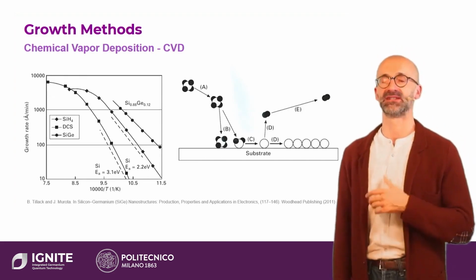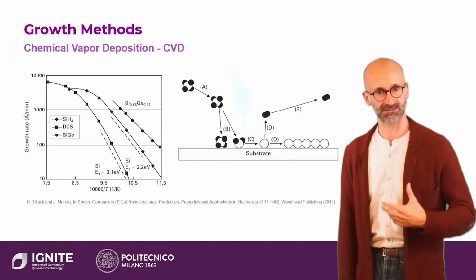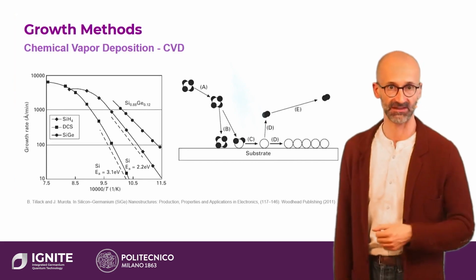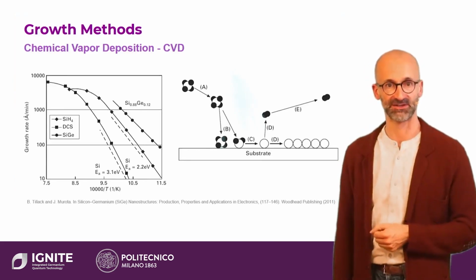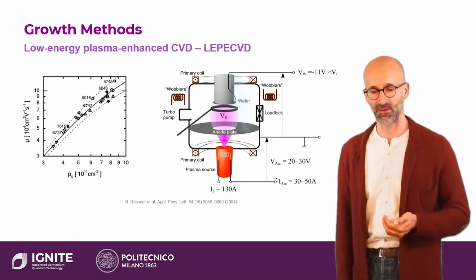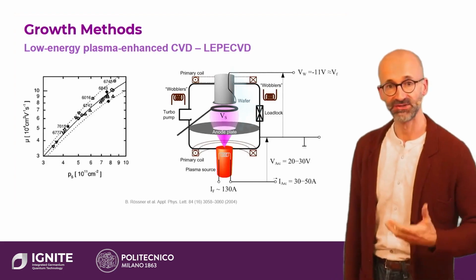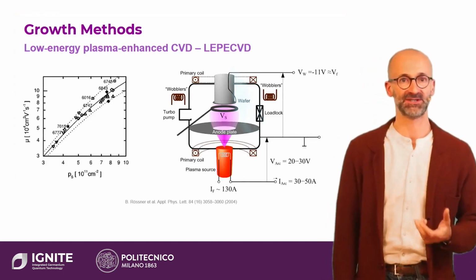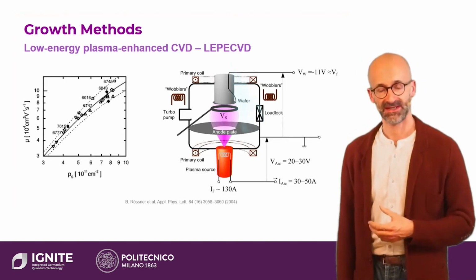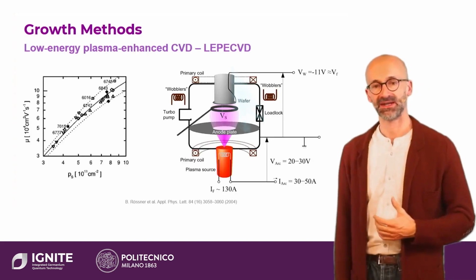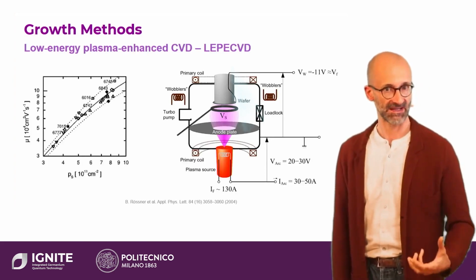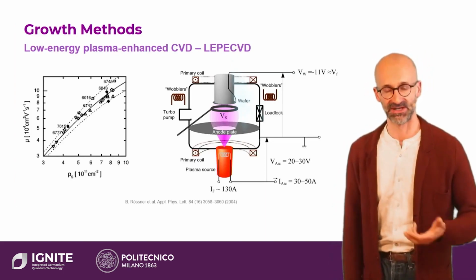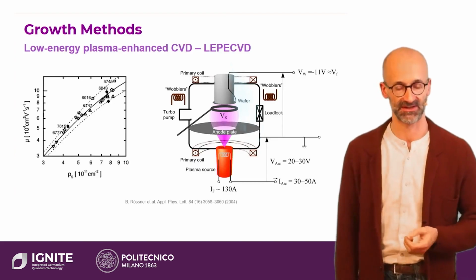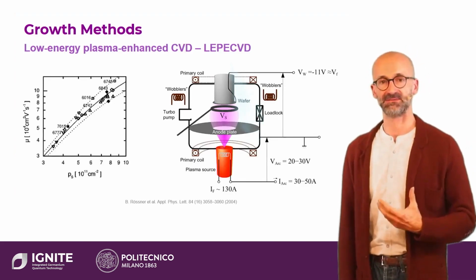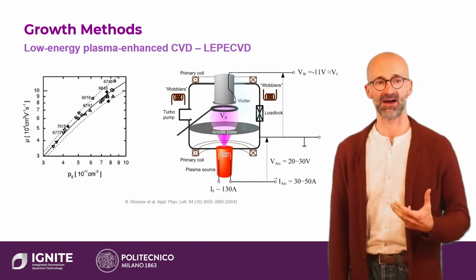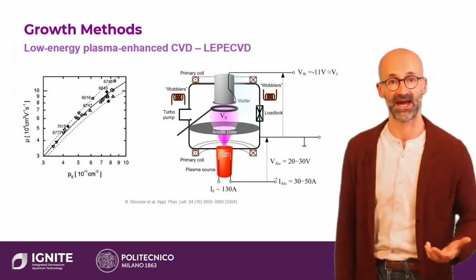However, being an industrial tool means that there is a large amount of expertise behind this system, so a lot of knowledge is building up on how to grow the best quality material, and in some cases even virtual substrates are available at a commercial level. The system, however, that we use at the Politecnico di Milano uses a plasma to enhance the chemical vapor deposition. And critically, the plasma has a low energy. That means that instead of being, for example, a typical radio frequency plasma where the ions have a large energy and they can damage the crystal, and in fact this kind of plasma-enhanced CVD is useful for amorphous materials such as oxides and nitrides. In this case, the low energy plasma-enhanced chemical vapor deposition means that the ions do not have such a large amount of energy, means that the crystal is not damaged.